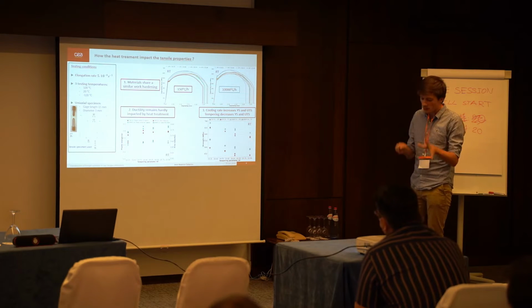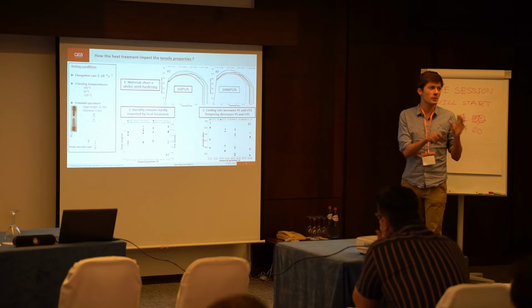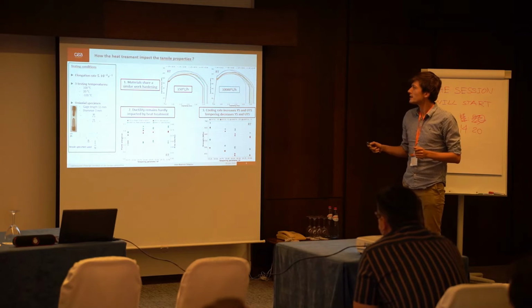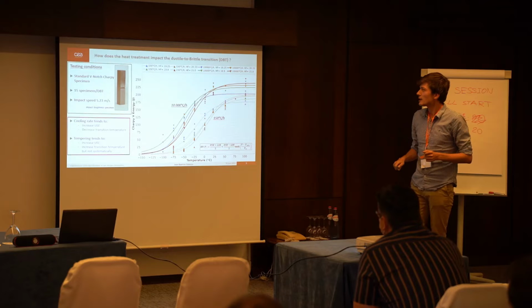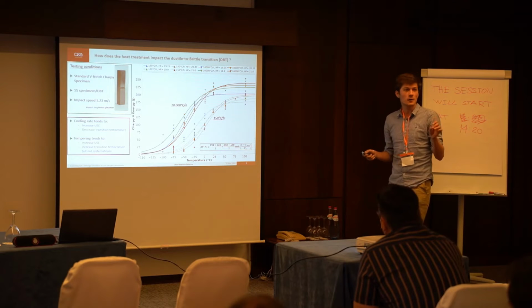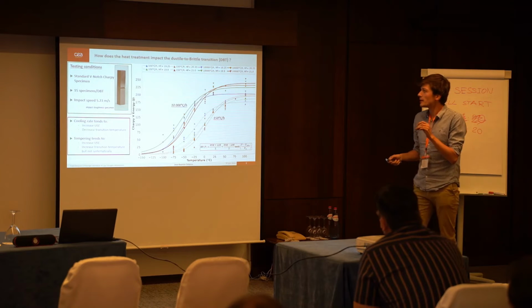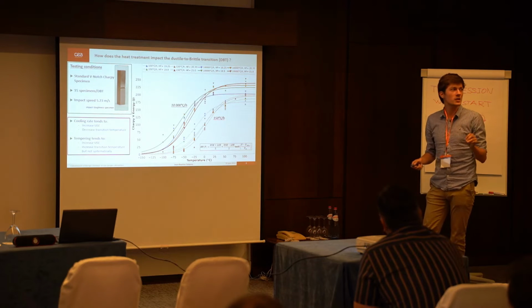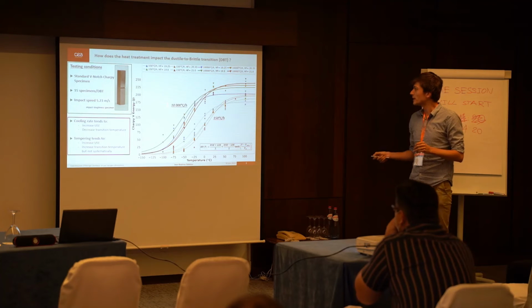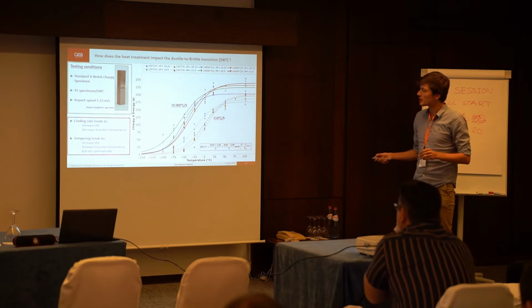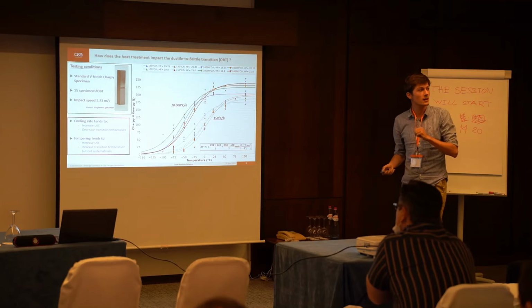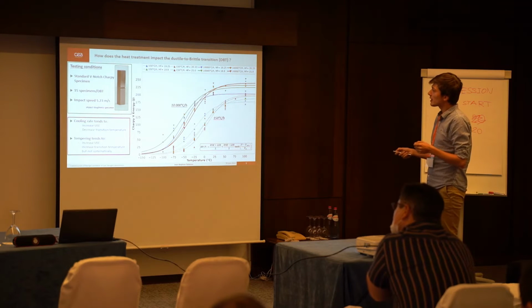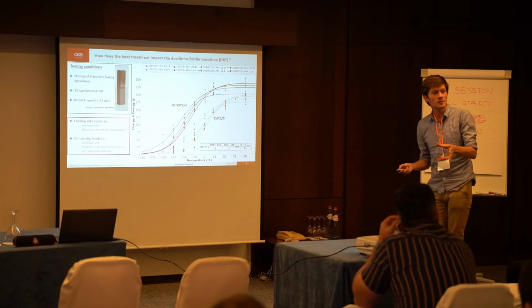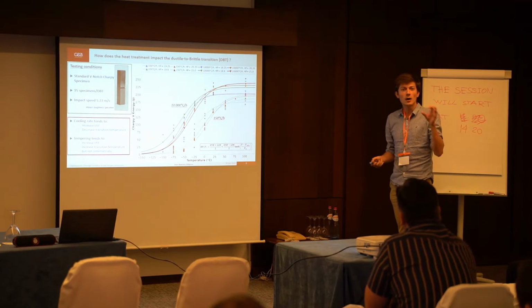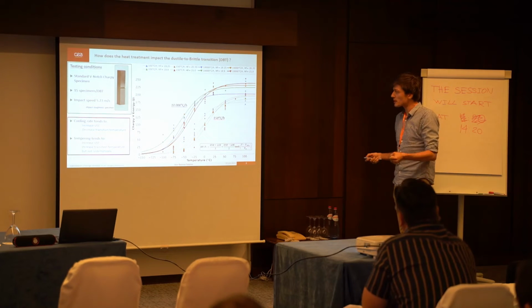So, now that we have seen the most basic properties for the material, we can look at the impact toughness properties. For each of the 8 materials, we have done 15 instrumented Charpy tests. And you have here the ductile to brittle transitions for all those 8 materials. And you can see the significant impact of the cooling rate on the impact toughness properties.